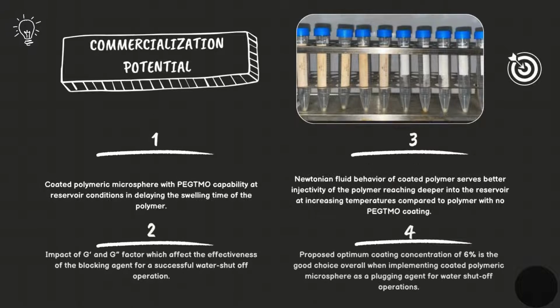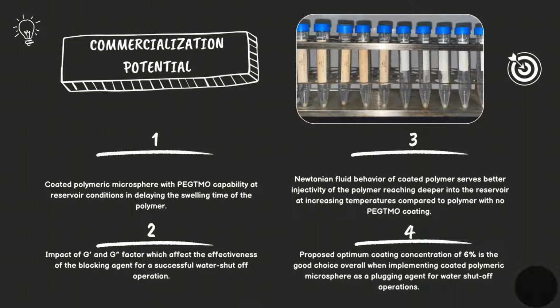Moving to commercialization potential, firstly, the coated polymeric microsphere with PEGTMO is capable at reservoir conditions of delaying the swelling time of the polymer. Secondly, the impact of G' and G" factors affects the effectiveness of the blocking agent for a successful water shut-off operation. Thirdly, the Newtonian fluid behavior of the coated polymer serves better injectivity, reaching deeper into the reservoir at increasing temperature compared to polymer with no PEGTMO coating. Lastly, the proposed optimum coating concentration of 6% is the good choice overall when implementing coated polymeric microsphere as a plugging agent for water shut-off operations.